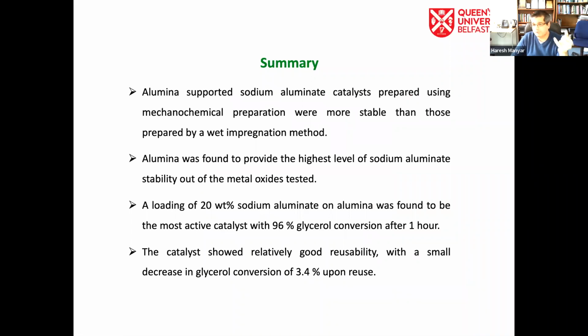The advantage of the material prepared by mechanochemical synthesis was that it was not making any aluminum hydroxide on the surface, which we would find from the wet impregnation methods. So that's why this was more robust, with better recyclability.